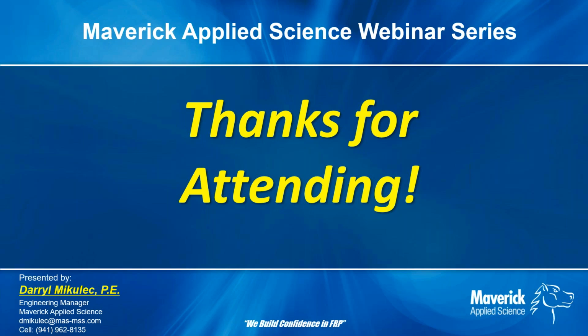At times it is. I wouldn't say always. This was basically resin capped in a sulfuric acid service, which is probably a little more severe than average, yet at this point it operated for 18 years with no issues. We weren't seeing breakdowns of the joints, didn't see huge contamination and deterioration of the edges of the joint, and in the cross sections that you showed, pretty much the edges were clean cuts.